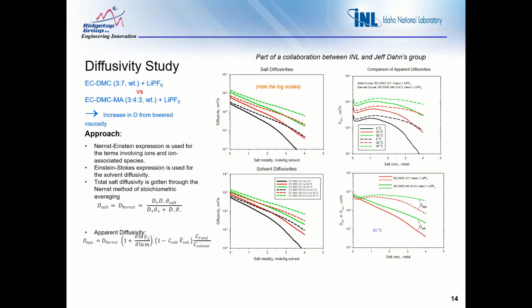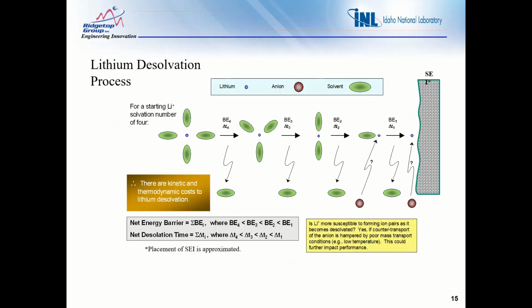Okay, next slide. So equally important to battery electrolytes is what happens with the solvated lithium, or I should say cation in general, as it shuttles back and forth between the electrodes during cycling. So it has to become desolvated in order to be inserted into the active host, either the anode or cathode. So there's a cost thermodynamically or energetically to do that, as well as kinetically or time-based. As we follow this lithium here, starting at the left-hand side, the lithium is a little blue sphere and the solvent are the green ellipsoidal shapes shown there.